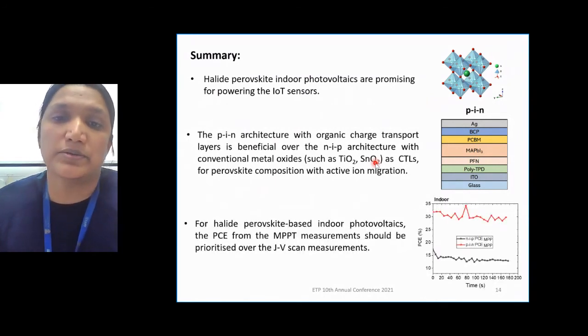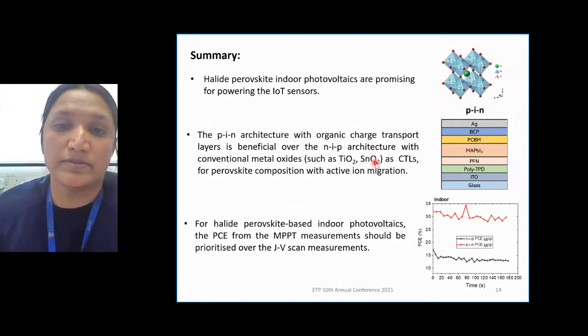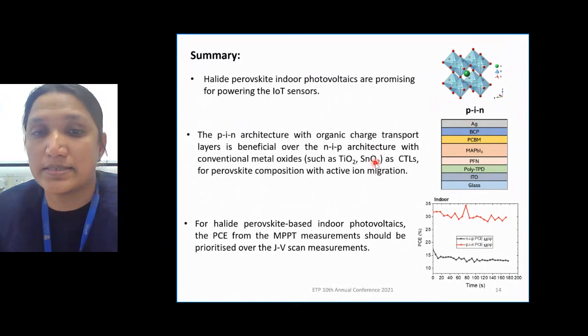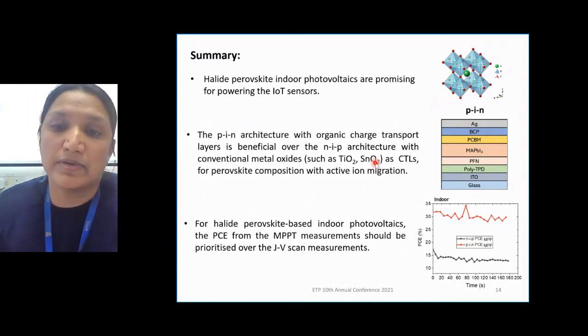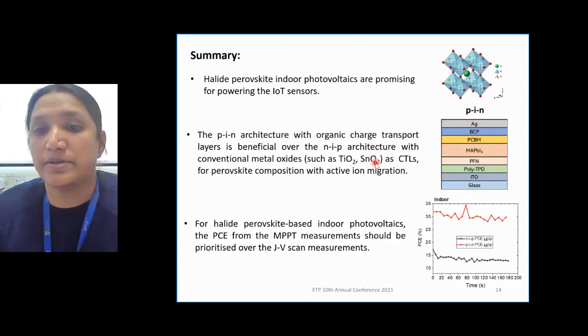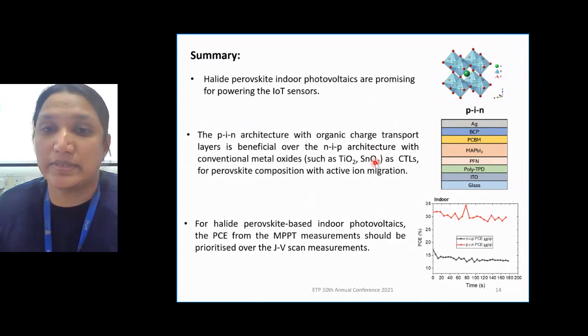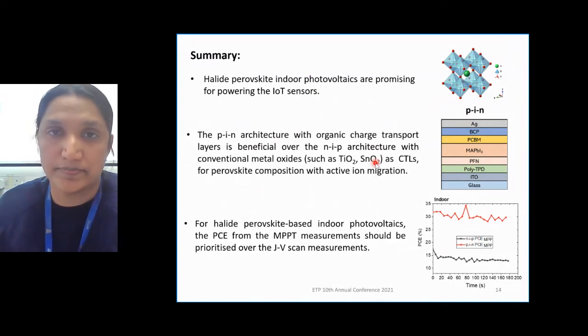And also we have observed that for halide perovskite based indoor photovoltaic devices, when there is hysteresis effect, the power conversion efficiency from maximum power point tracking should always be prioritized over the JV curve measurement, because the JV curve will not be reliable when the devices have this hysteresis.